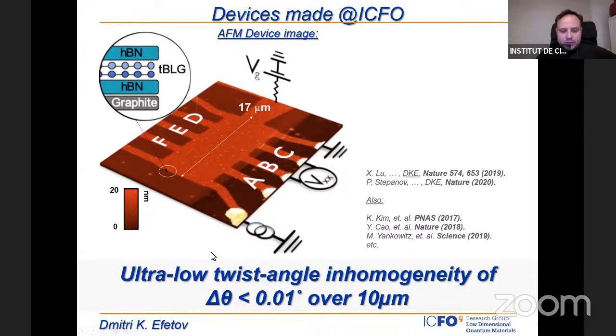Another thing I want to say is that one of the challenges in this field was to make homogeneous twist angles across the whole device, because you can imagine that in an assembly process like that, the twist angle might vary a lot. And indeed this is true. You have to understand that graphene has the mechanical property of Saran wrap. If you try to glue two layers of Saran wrap one on top of another, you have to be very careful to align them. Very often you find faults, you trap bubbles, and all the properties you can think of when you wrap a sandwich. So in our lab, we were able to develop a process which reduces this wrinkle formation. Now we have devices which are relatively twist angle homogeneous, with a twist angle variation below 0.01 degree over 10 microns.